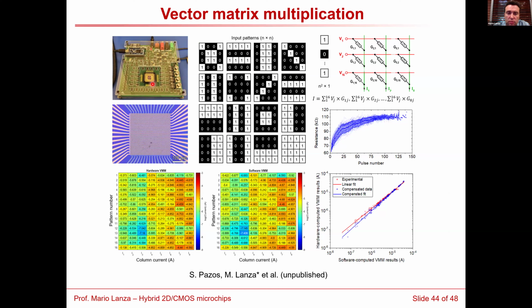And we have tested it with 1 kilobit, so a 32 by 32 crossbar array of gold boron nitride gold devices, the size is 25 micrometers square. So it's the old samples. And here we don't have the transistor.